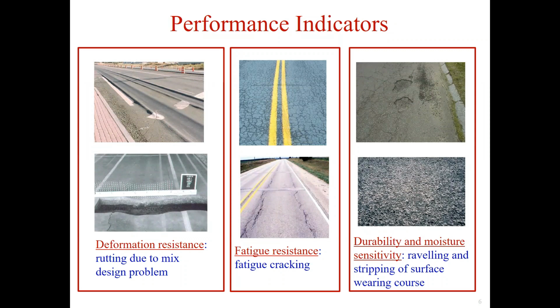Durability and moisture sensitivity are another two performance indicators, and the corresponding issues are raveling and stripping of the wearing surface. Raveling is the progressive disintegration of a pavement surface through loss of both binder and aggregate. Asphalt stripping is essentially asphalt raveling in reverse. So instead of the surface coming apart, disintegrating and exposing the lower layers, the asphalt in the lower layers falls apart first and damages the upper layers.